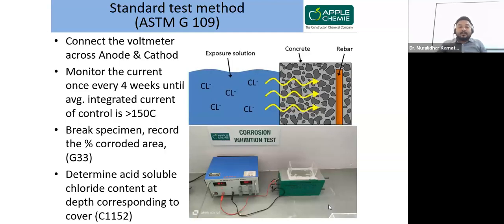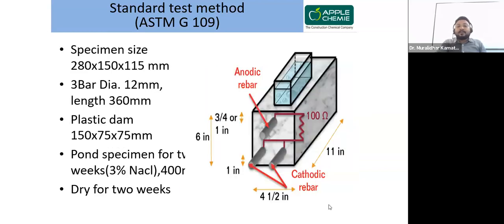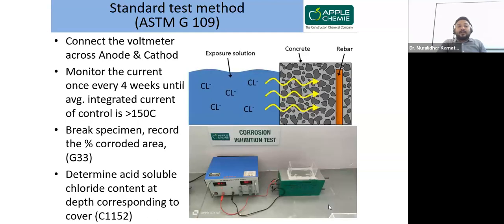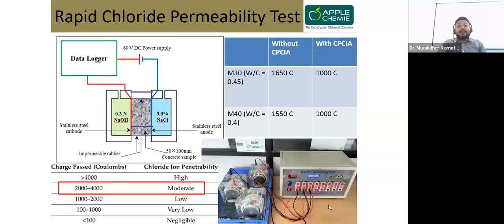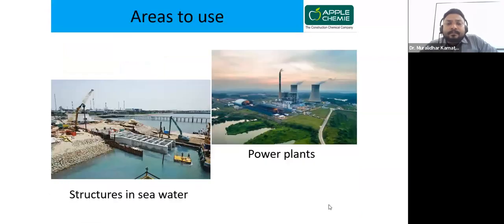And here you can see we are also testing a specimen exposed to the chloride solution. Sodium chloride solution will be kept in this. Then we expose the reinforcement to chloride attack throughout, and the chloride solution is kept over the concrete cover surface. Again, the RCPT with and without: here also it is going to reduce. I already explained this test, right?